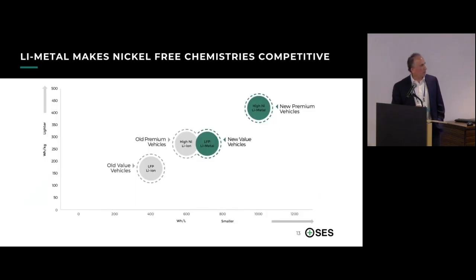Just looking at lithium metal makes nickel-free chemistries more competitive. So basically, what this chart is showing, if you look all the way on the right, the green circle is the energy density of our lithium metal cell paired with a high nickel cathode. So we're roughly around 400 watt hours per kilogram. And if you look in the middle of the chart, today's lithium-ion batteries paired with a high nickel cathode are around 260 watt hours per kilogram. So we're roughly about a 50% increase.